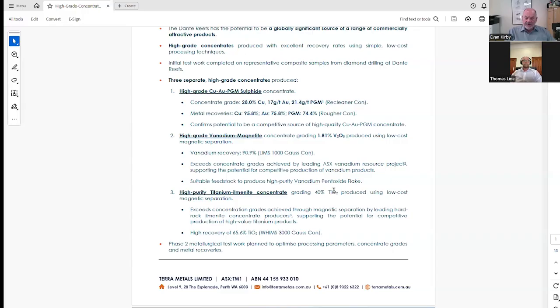We've got this full range of minerals, and as the titanium content increases, the magnetic characteristics change. The magnetite and titanomagnetite can be recovered by low intensity magnetic separation, and progressively higher magnetic field strength is required to recover the more titanium rich products. We've exploited these differences in magnetic susceptibility to recover, first, a magnetite and titanomagnetite vanadium concentrate, and second, an ilmenite concentrate.